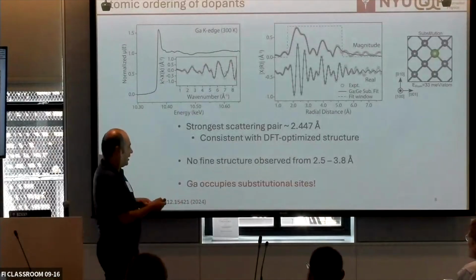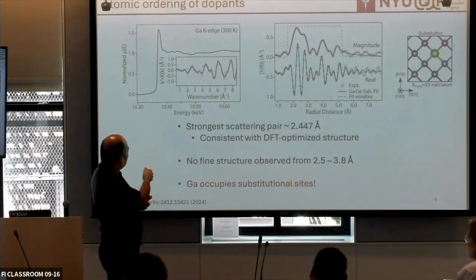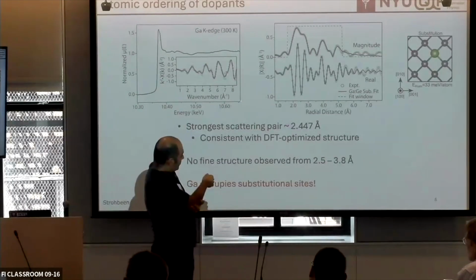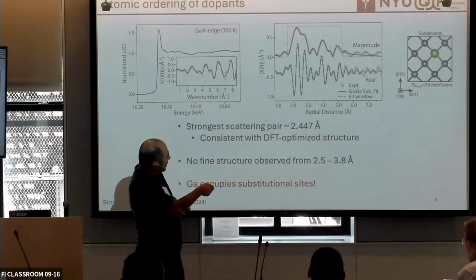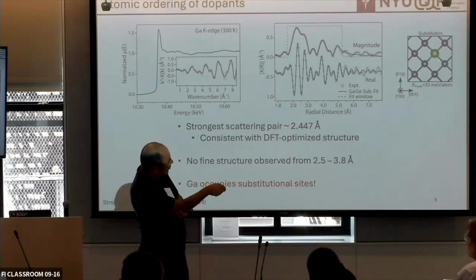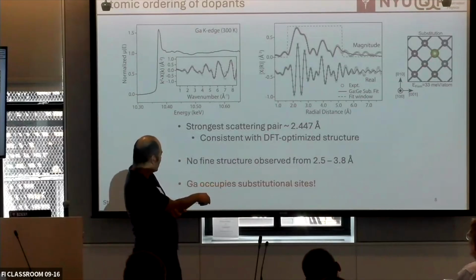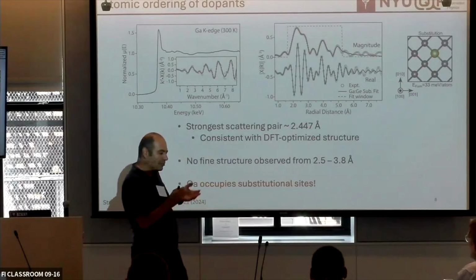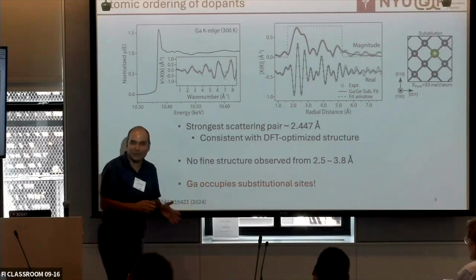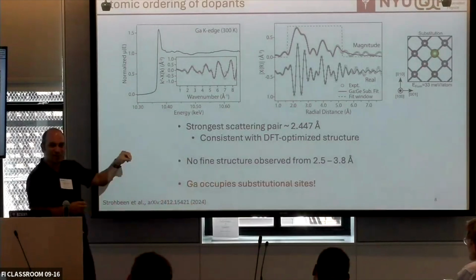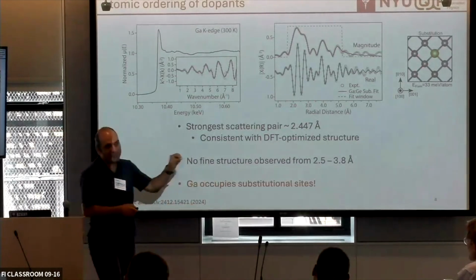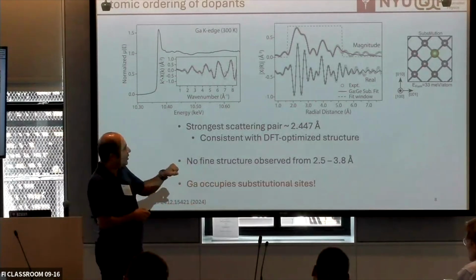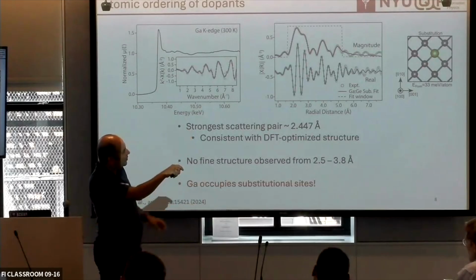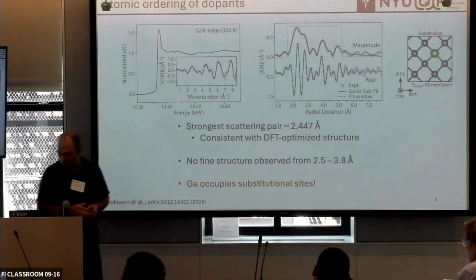This is not my expertise, but our friends over there did the X-ray measurements, and what they find is consistent with the DFT calculation: one atom is substituted, and there is no fine structure that we could observe. The final theory-experiment conclusion is that we managed to successfully substitute one gallium in the germanium lattice. The fit and everything is consistent with this picture. So that's the overall thing.